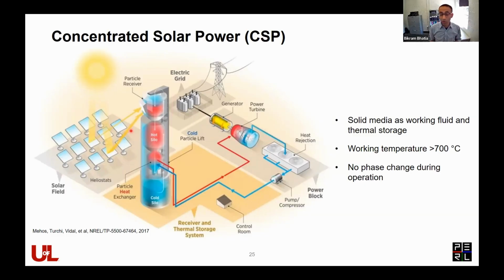And then there is also a lot of work with molten salts, which change phase from solid to liquid. But again, they have challenges associated with leakage and corrosion, some of the things that I mentioned earlier. But there was also a lot of work done on solid particles, basically sand, alumina silica sand, as a heat transfer media for CSP application. And over the several decades, they've basically zeroed in on solid particles as a heat transfer media as the best approach forward for CSP.